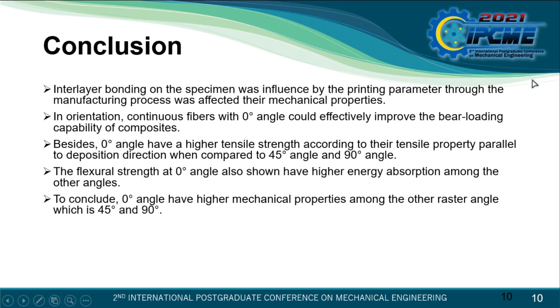In conclusion, the printing parameters affect the mechanical properties in the process. In orientation, continuous fiber at zero angle could effectively improve the load-bearing capability of the composite. Besides, the 0-degree angle has a higher tensile strength, according to the tensile property parallel to the deposition direction, compared to the 45-degree and 90-degree angles. The flexural strength at zero angle has shown higher energy absorption. To conclude, the zero angle has higher mechanical properties than the other angles, which are 45 degree and 90 degree.